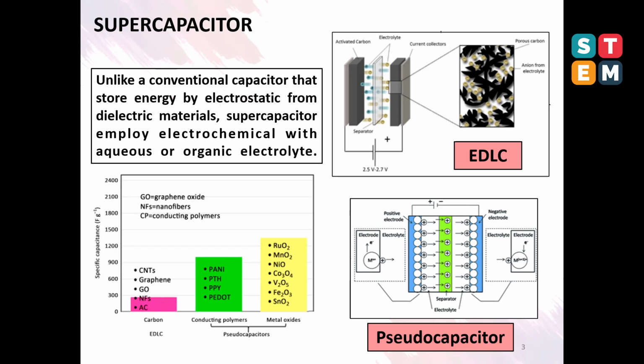The EDLC type has some weaknesses: its efficiency is limited by the surface area of the material. That results in the EDLC type exhibiting lower specific capacitance than the pseudocapacitor. However, the pseudocapacitor has quite low cycle stability. It is interesting to develop higher performance pseudocapacitors.